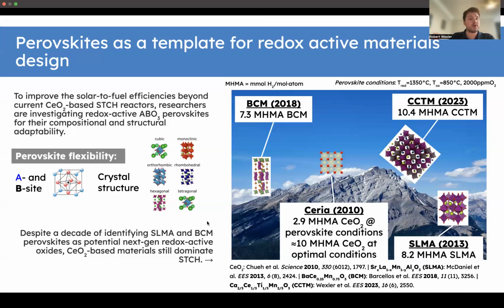I'm just showing 6 of the more common ones here, ranging from cubic and monoclinic to hexagonal and tetragonal. And these can also host things like octahedral tilting, which can reduce symmetry, and Jahn-Teller distortion, as well as different octahedral arrangements such as corner sharing, edge sharing, and face sharing. So there's really a lot of compositional and structural flexibility in perovskites, and this has been exploited to some extent in the development of materials like strontium, lanthanum, manganese, aluminum oxide, SLMA by McDaniel et al., as well as barium, cerium, manganese oxide, BCM by Barcelos et al.